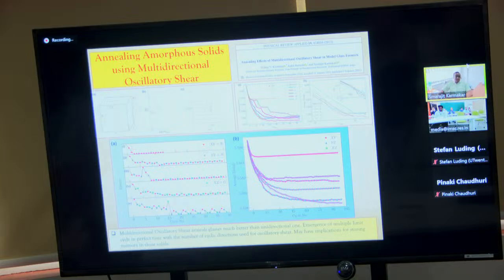For example, you see this panel where if you do unidirectional oscillatory shear on the XY plane, then you get a steady state which has only one energy scale. But if you do oscillatory shear in 3 directions, then you can reach a steady state which toggles through 3 energy states, which is very interesting in the sense that, which I may come back to if I have time, these states store memories. So if you do multiple-direction oscillatory shear, there are possibilities that you may be able to store multiple memories along those directions, which is not yet achieved, but the possibility still holds.